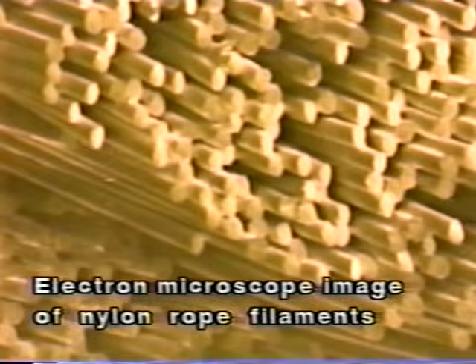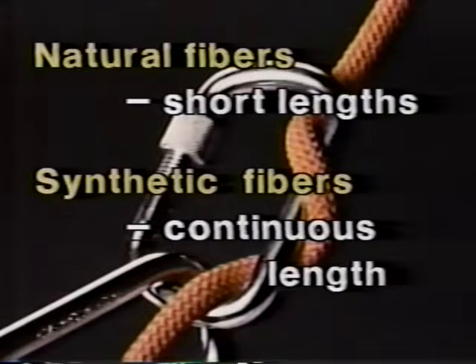There's a great deal of concern and a great deal of old data about the flexibility of ropes and sheave diameters, for example, as opposed to rope diameter. We see these large ratios, 20-to-1 type things. And the reason for that is because natural fibers are in very short lengths. They're little pieces, maybe 4 inches long, maybe 12 inches long, but they're still short. And a synthetic fiber that's used for rope, for all practical purposes, is the entire length of the cordage. The same fiber runs from one end to the other. So by flexing it, you don't have these little short pieces that are just overlapped being bent until they fall apart from each other. So the going away from natural fiber ropes to synthetic ropes has made rescue much safer by orders of magnitude, as far as rope failures are concerned in the field.